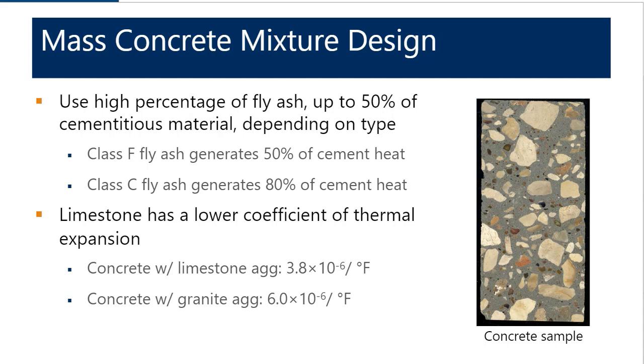It can help reduce the amount of heat released by a concrete mixture by up to about 50% of the equivalent amount of cement that it replaces. Class C fly ash is not as efficient as Class F fly ash at reducing temperatures. Typically, it generates about 80% of the heat of the cement that it replaces. And then slag is a little bit less efficient, typically between about 80 and 90% of the heat of the cement that it's replacing. But using SCMs is a very effective way, especially when it's Class F fly ash, of reducing your heat signature for your concrete mix.